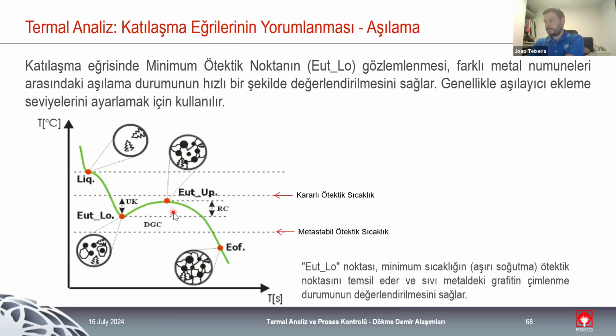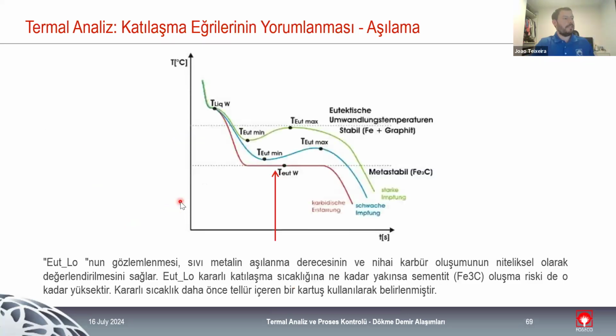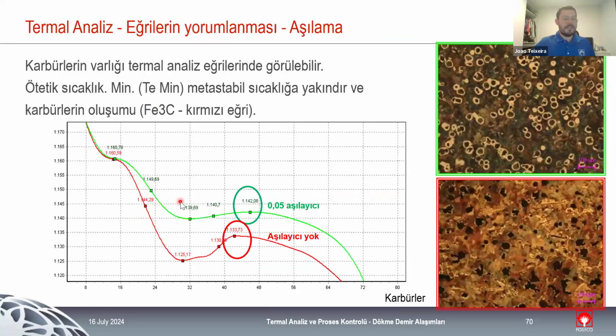This is just related to the importance of the eutectical minimum and eutectical maximum. The inoculation step happens between these two temperatures. And we can see here, this is a good example for us to discuss this. In the red curve, we don't have any type of inoculation. And in the green curve, we have a small amount of inoculation.